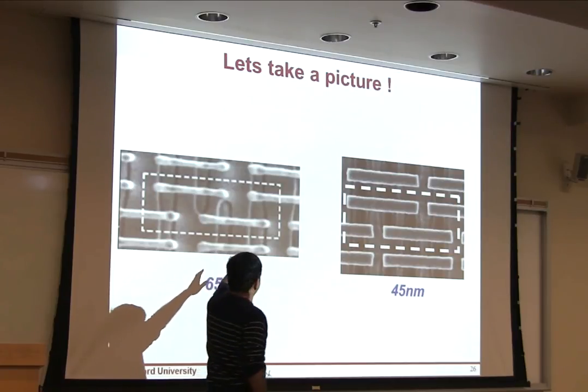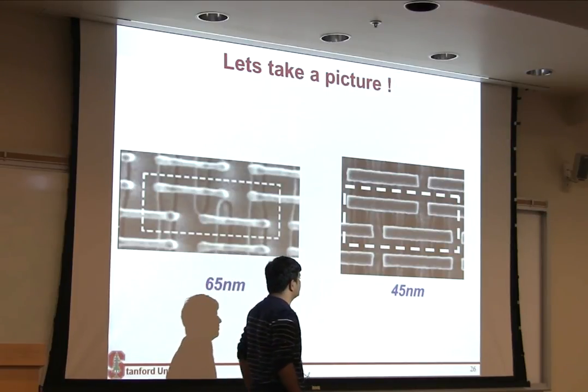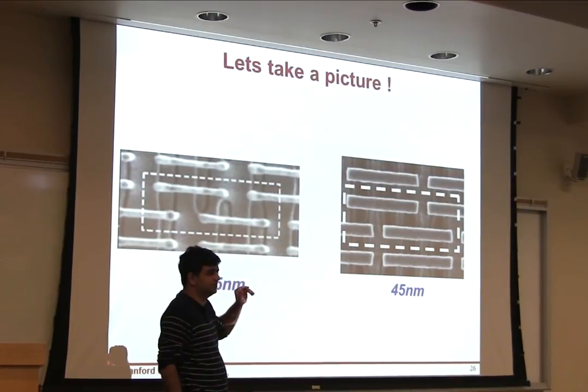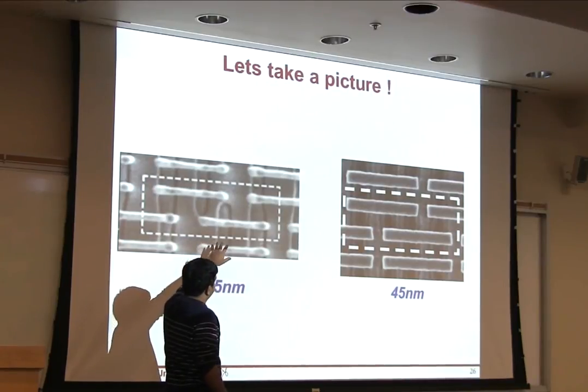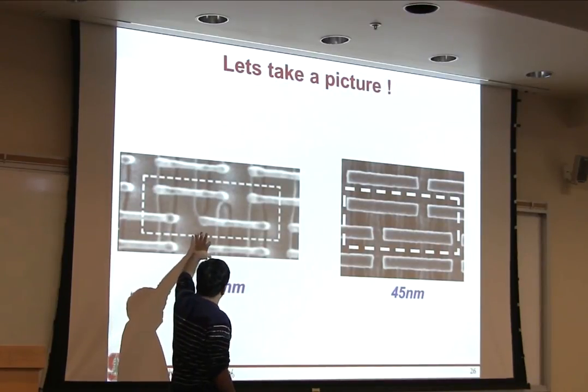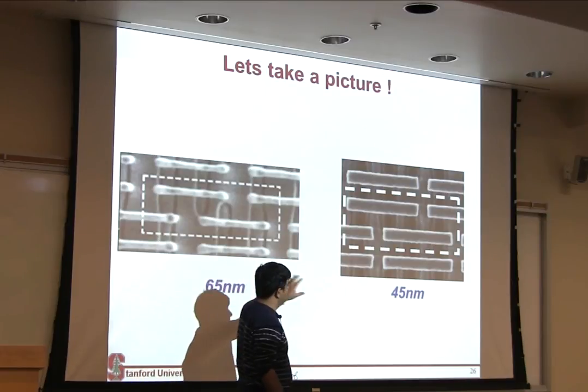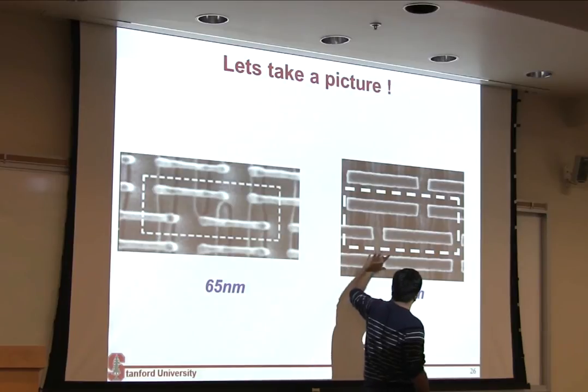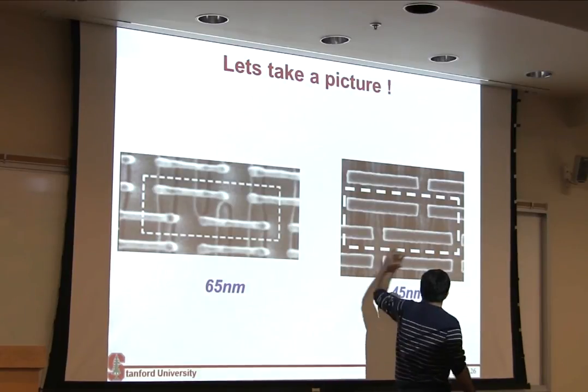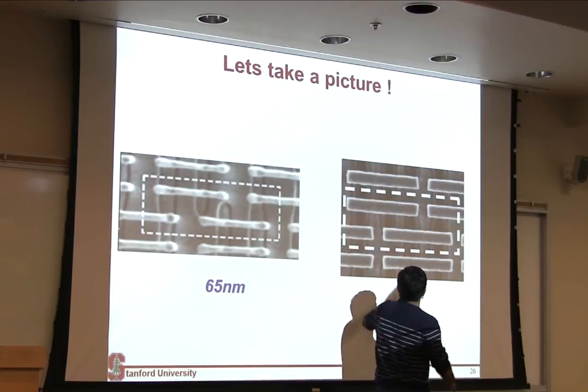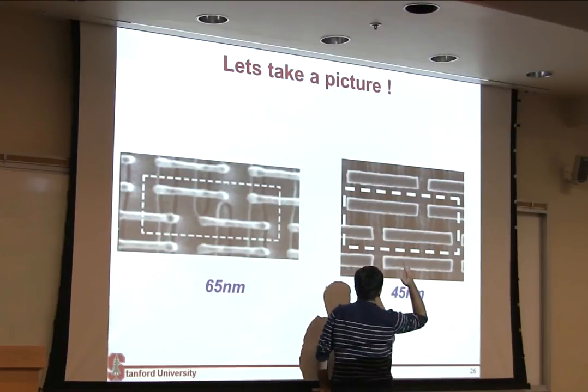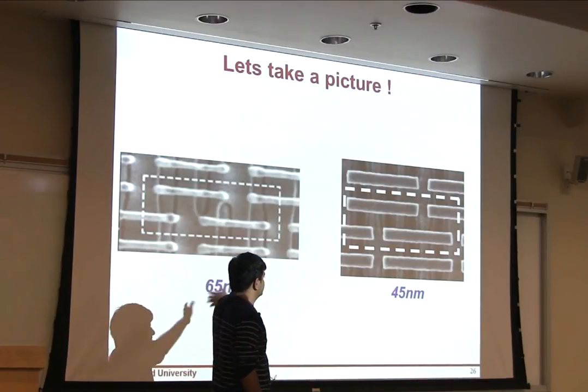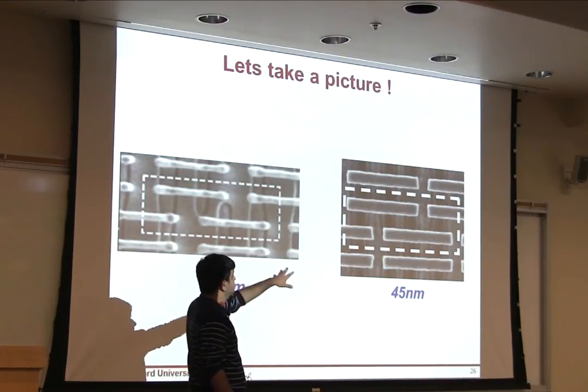So the question was: why did the lines actually become better from 65 to 45 nanometers? The reason they became more rectangular is that at 45nm, people used to print in two steps. You print straight lines — all of them straight together — and then there was additional printing done to cut them where you need to cut them. So it's two masks instead of one to make the same feature. That's why they look more rectangular.